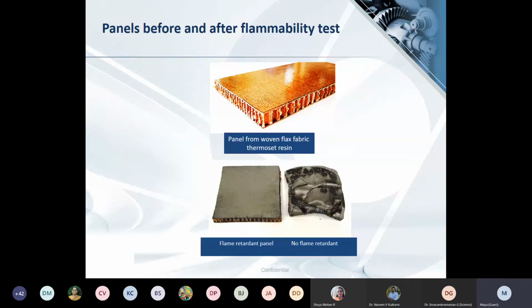So this is just a picture of the panels before and after testing. So on top you can see the panel. Below left you have the flame retardant panel, and you can see that even after burning, the panel is compact and has not collapsed. While a panel without any flame retardant is completely collapsed. So it's also important that the flame retardants that you do choose is helping to maintain the compact structure of the panel.